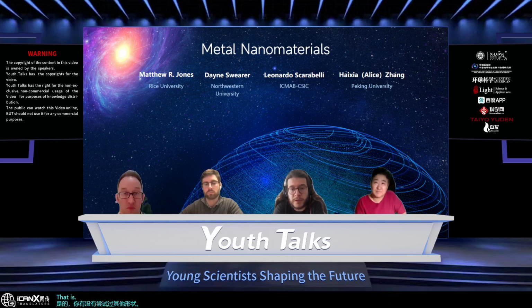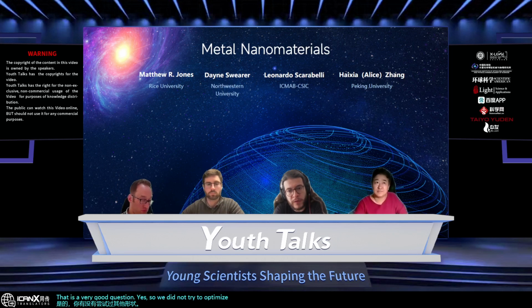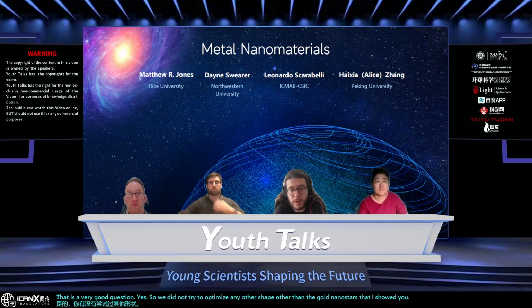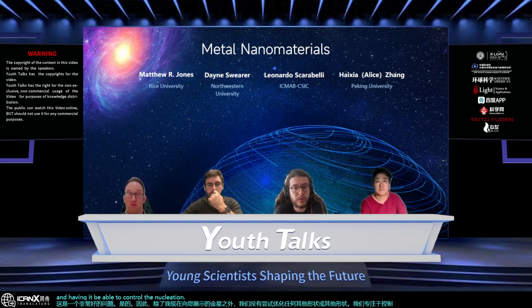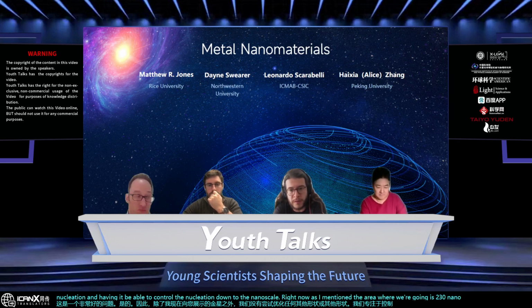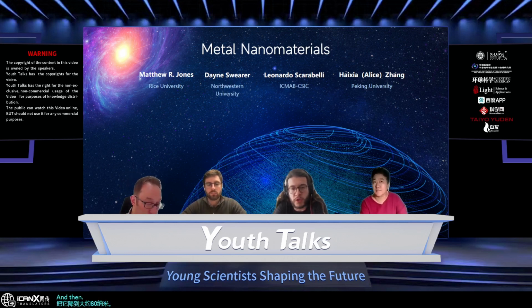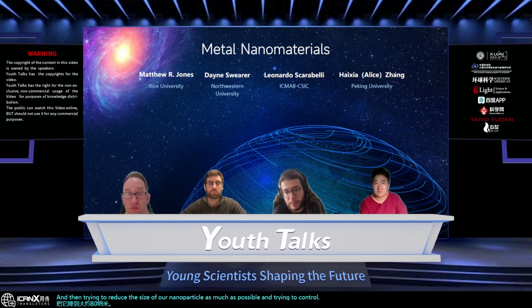That is a very good question. Yes, so we did not try to optimize any other shape other than the gold nanostars that I showed you right now. We are focusing on controlling the nucleation down to the nanoscale. Right now, as I mentioned, the area where we're growing is 230 nanometers. We are looking to bring it down to about 80 nanometers, and then trying to reduce the size of our nanoparticles as much as possible and trying to control their shape. That would be the next step.